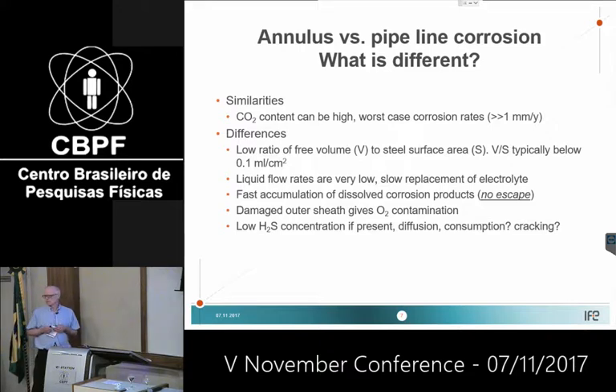There are some similarities, but also many differences between the annulus corrosion and more traditional pipeline corrosion. Similarities are that you have CO2 both places. You can have H2S. You have water. You have carbon steel. You have corrosion. And in both cases, you can get high corrosion rates if you have a reasonably high amount of CO2. But the difference is that this volume to surface ratio is so small in annulus. And all formed corrosion products cannot escape any place. Everything remains in annulus. In a pipeline, it goes to a separator. But here, it just builds up, and sooner or later, it has to precipitate and form solids.